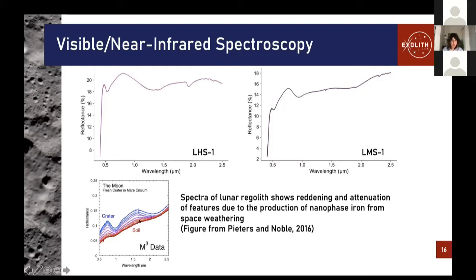So the plot that I've shown at the bottom left here is a plot from the M-cube data on the Chandrayaan orbiter, using the spatial resolution available. This was from Pieters and Noble 2016. So this is looking at mature lunar soil and then moving toward a crater with fresh soil. And you can see how the mature soil is very red and the features are very attenuated. And then as you move to the fresh, less weathered material, the red slope starts to decrease and the absorption features return.